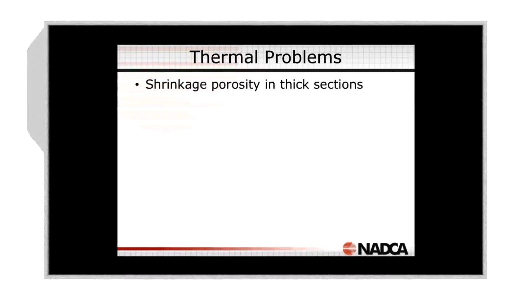Thermal problems. Shrinkage, porosity, and thick sections. You can't always stop the shrinkage porosity, but in most cases you can. So if you know you've got a thick section, you can do a quick review of thickness using CAD or using some of the other simple simulation packages for thermals. And you can see that there are thick sections and you've got to cool them. So you put the appropriate cooling in, that's it. As long as that casting section freezes before the surrounds, then there will be no shrinkage. Shrinkage porosity occurs because aluminum, zinc, magnesium, brass all shrink as they freeze.